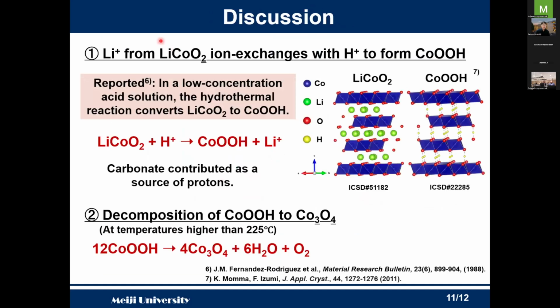So there is a discussion of the reaction mechanism. First, lithium from LiCoO2 ion-exchanges with protons to form cobalt oxyhydroxide. It has been reported that in low concentration acid solution, hydrothermal reaction converts LiCoO2 to cobalt oxyhydroxide, meaning LiCoO2 to CoOOH.